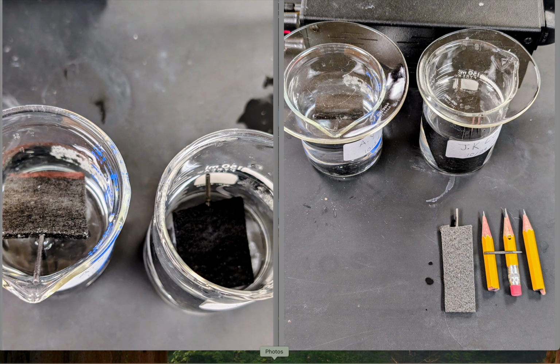During the course of 45 minutes at 22 degrees Celsius in the lab, we saw hydrogen evolution at the cathode. We saw the graphite felt turning dark. The plating bath went from colorless to a light yellow color. That's the manganese species, which helps to create more uniform oxidation on the felt.